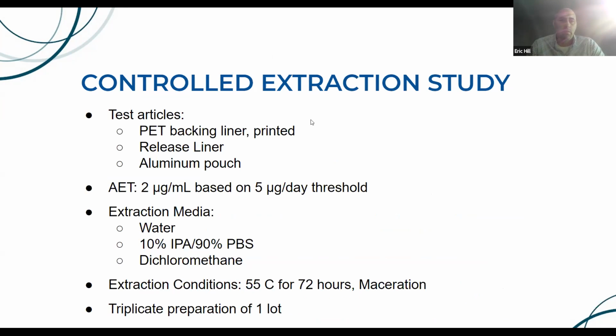And so the first thing we did is we did a controlled extraction study. Our test articles were the backing liner printed, the release liner, the aluminum pouch. The AET that we calculated for this study was 2 micrograms per mL. And again, that was based on a 5 micrograms per day threshold, which I explained earlier. Our extraction media were water, 10% IPA, 90% PBS, and dichloromethane. We extracted under maceration conditions at 55 degrees C for 72 hours. And we did triplicate preparation of 1 lot.